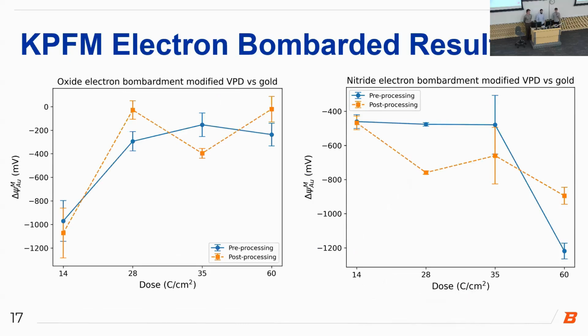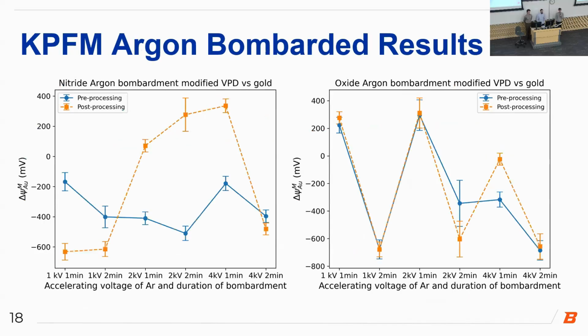With regards to electrical characterization, there is a significant difference between pre and post processing for our nitride samples with electron bombardment, but there is not a significant difference between pre and post processing for our oxide. The same can be said for our argon bombardment, with a definitely more pronounced difference for our nitride samples. And this is in agreement with literature that we found about nitride being more sensitive to these processes than oxides. I'll now hand it off to Joe to continue analysis of our results.